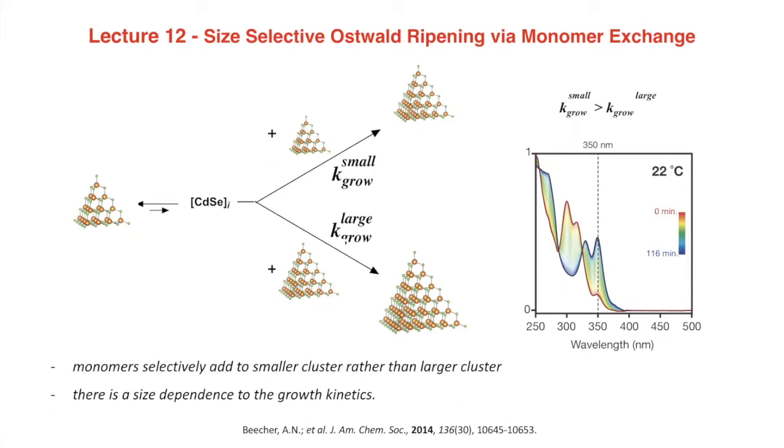And so I think this is a very suggestive finding that, in fact, growth dynamics of surfaces are size dependent, and that even under conditions where you have attachment limited growth kinetics, where the thermodynamics of that surface and the barriers to attachment are the dictating force in the growth kinetics, you can still have a size-dependent growth rate.